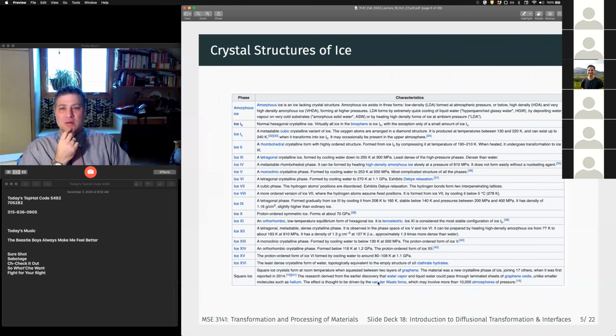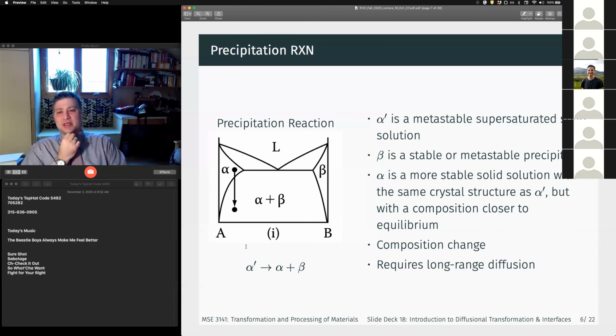substances, right? Most importantly are phase transformations like the precipitation reactions, right? Where we will hold for a while in a single phase region, quench down in temperature. So now we have a metastable single phase that will then, in this case, decompose. We have supersaturated metastable alpha. Beta, which is rich in B, will precipitate out, forming particles. And the composition of alpha will get leaner in B as B-rich beta precipitates form, right? This requires long-range diffusion, and there's a global composition change. I mean, not a global composition change, but the composition of each phase changes, right? So this requires that we have B diffuse over long distances to form these beta precipitates, right?